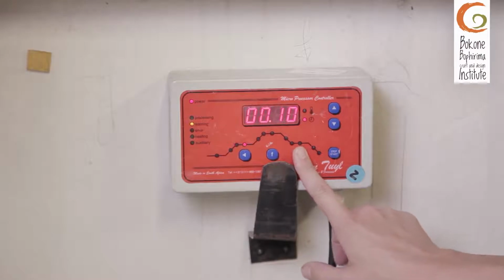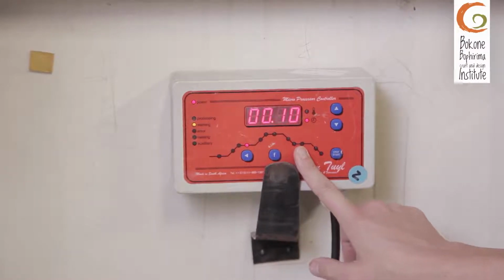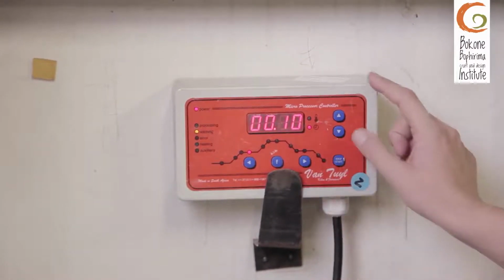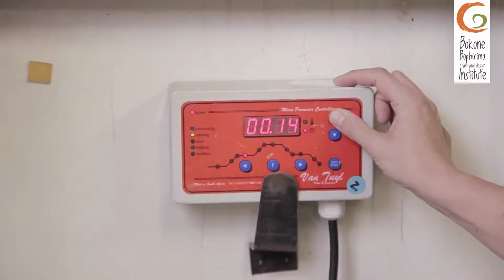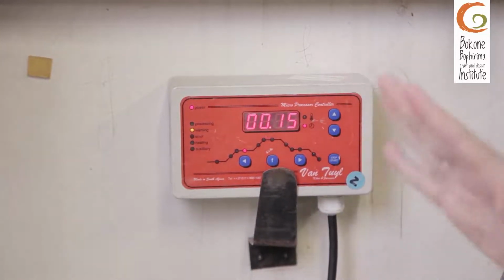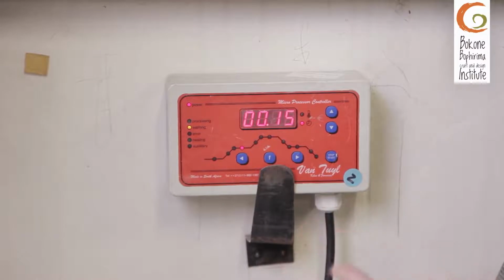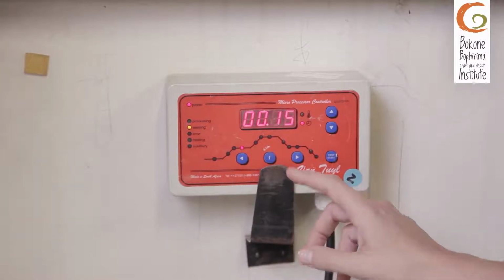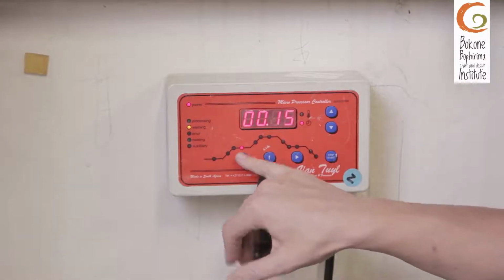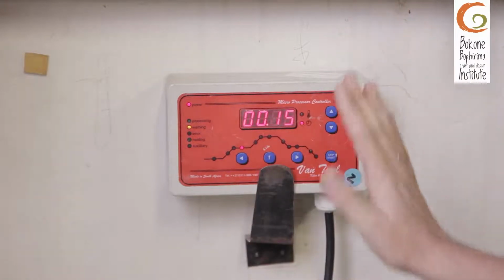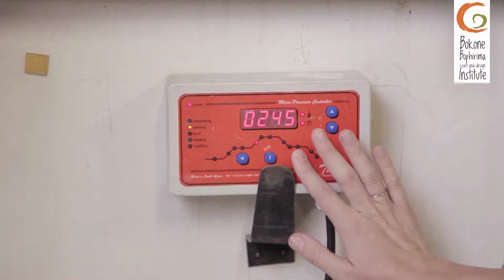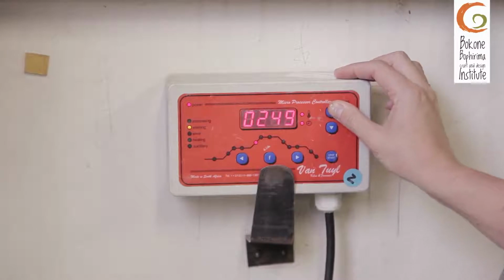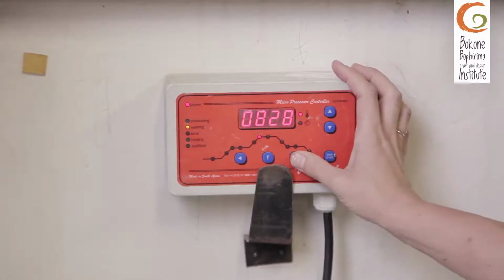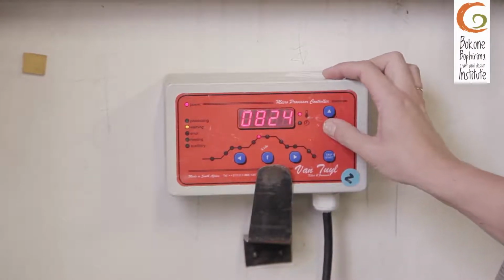I am then going to hold that temperature for 10 minutes. Actually, no, I'm going to hold it for 15 minutes. Reason being because I've got two layers of glass and I want to ensure that my bottom painted layer is also at 580 before taking it up to its top temperature. I'm then going to take the glass up 250 degrees an hour up to my top temperature of 820 degrees.